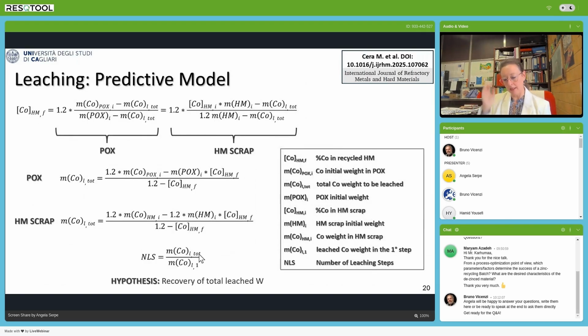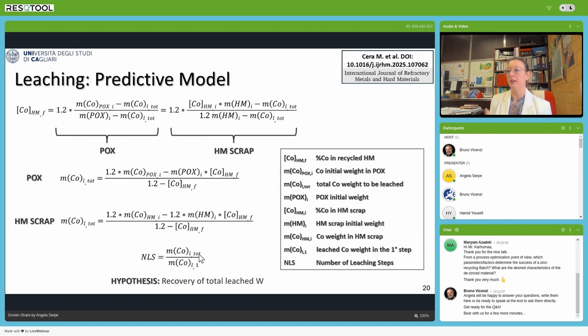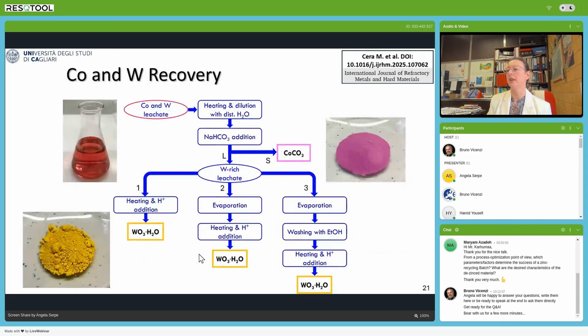The fact that we can divide the process in different steps made us able to design a predictive model to predict the number of stages that we can apply on the oxidized material to obtain a final tungsten carbide material with a specific composition. Of course, if we leach cobalt and tungsten from oxide material, we then have to recover them from the solution in a selective way.